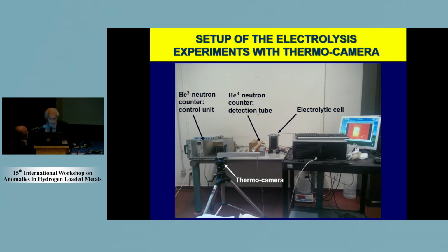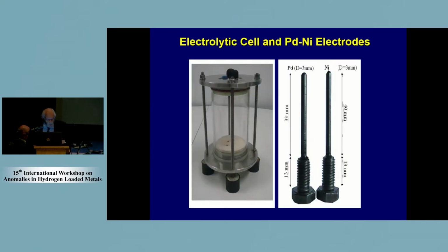Then we have the cell, the electrolysis cell, and in the bottom part you can also observe the thermocamera, which is essential to have our results related to calorimetry, of course. This is a detail of the cell. You can see its structure is not a large object, of course. There are 2 electrodes, palladium and nickel. The length is about 4 centimeters, and the diameter is 3 millimeters. Then they were immersed, of course, in a solution of potassium carbonate.